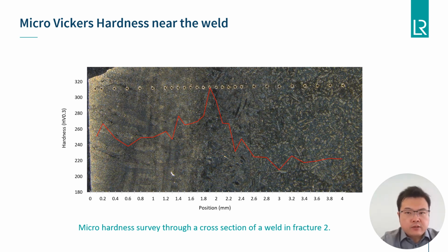To better understand the effects of the welding on the mechanical properties, we carried out a very localized Vickers hardness survey of HV0.3 through the welded section. The slide shows the relative micro-hardness results of the material with respect to the depth through the welds in the second part of the fracture.